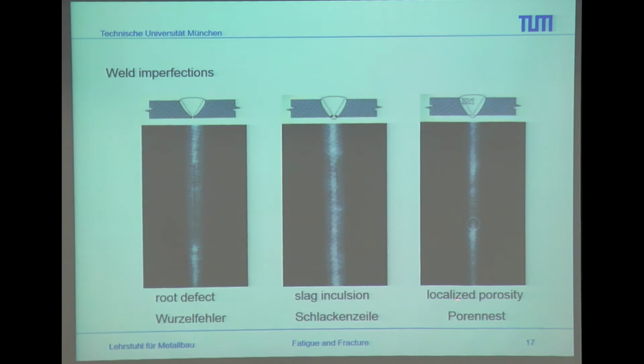And then the next one, localized porosity. So a porous welded part has some pores, and the pores are also the starting point of the cracks in the structure. Due to this, in the X-ray you can see how big the pores are, how many pores there are, and what the amount of pores is. And so you can say, does your welded part or your weld seam satisfy your quality management or also your quality regulations?